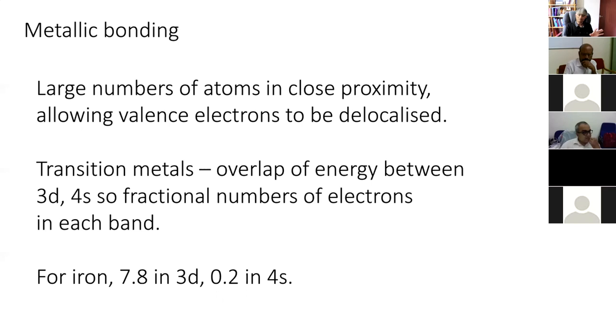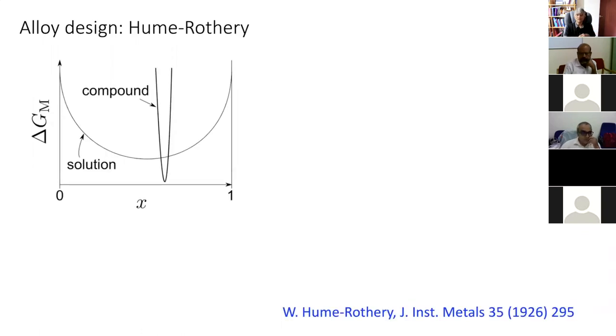So we need to think about large differences in the number of valency electrons between the elements. Because if there are large differences, then according to the empirical Hume-Rothery rules, you will not tend to get a solid solution.